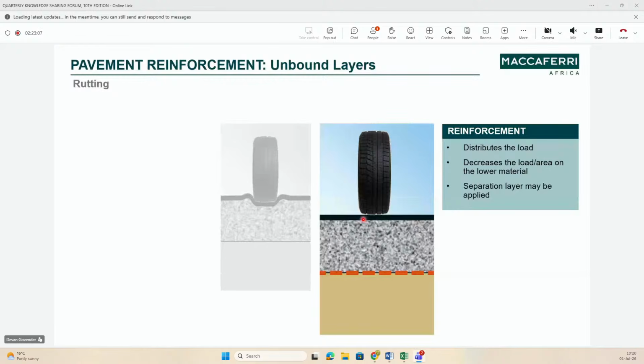Now, when we apply the design principles for reinforcement in the layer works, there's two key design approaches. The one design approach is we say, okay, this is our layer that's here. We design it in a traditional approach, and then we introduce grids in there. By introducing the grid, we reduce the thickness of that material. So that's design approach one: reduce the thickness of material and put in a grid. Design approach two is we keep the thickness the same, but we increase the pavement life. So you can go, for instance, from 5 years to 10 years, or 10 years to 15 years, simply by introducing this material into your pavement.